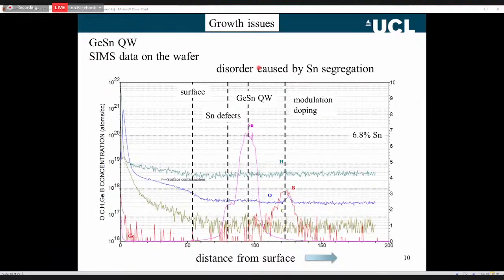So our collaborators that grow the wafers do X-ray on the system, and they know two things. They know that the layer is coherent with the barrier material. The barrier is germanium. Germanium-tin grows coherently. They also know that it's strained, in compressive strain.